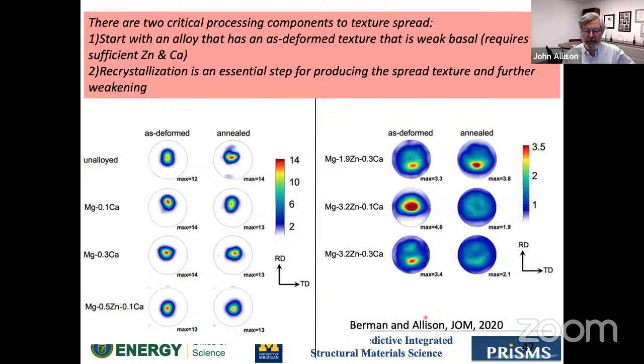And this is some recently published work of Tracy Berman in the center. Looking at as-deformed textures and annealed textures, you can see here, going through a range of alloys, we can soften this as-deformed texture. And we think primarily this is because of this changing of the ratio of c+a pyramidal slip to basal slip, that ratio.